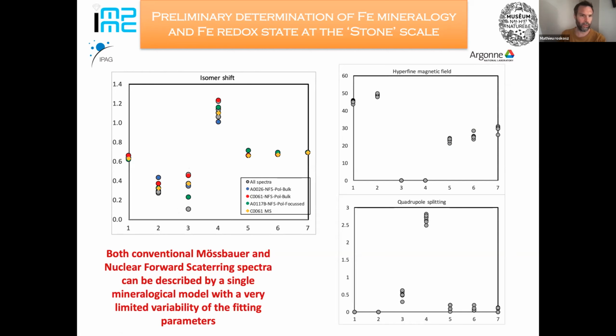Some of them are probably related to a poor quality of the fit, but some of them may suggest that we actually have 2 sites for iron 3+, one in serpentine and one in smectite, and they are not exactly the same coordination.